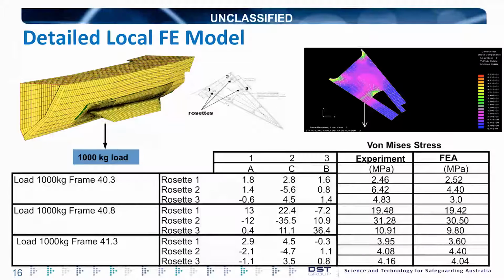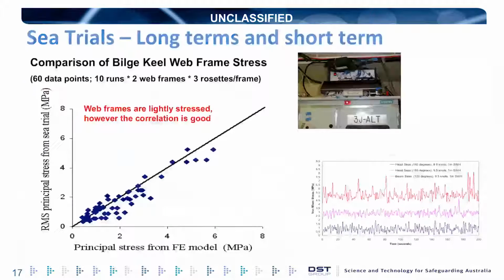And so you can see here that although the loads were fairly small, the comparison between the experiments and the finite element analysis was pretty good. So we were quite happy with our FEA model representing the real ship. Then the ship went out and did a sea trial, which basically means it travels at various speeds in various heading angles, and we measure the response for each sea state. We compared the measured response with the predicted responses, and again we got a fairly good correlation.